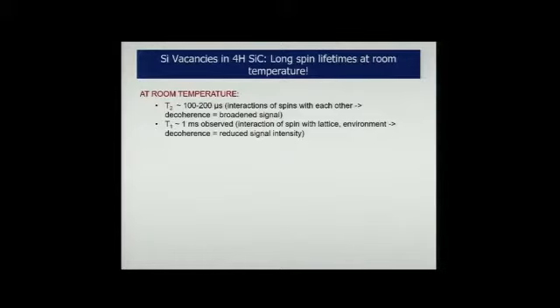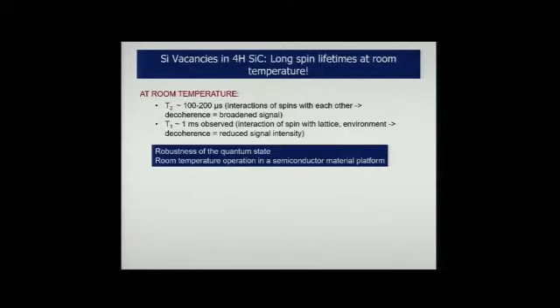And so decoherence has the net effect of reducing the signal intensity. These T2 and T1 times are on the order of hundreds of microseconds to milliseconds or greater. That is a long enough time, and there are ways of actually revitalizing the spin states. But those lifetimes at room temperature give us great hope for going further with these silicon vacancies as possible qubit candidates. So two other items on our wish list: the robustness of the quantum state, as indicated by the spin coherence lifetimes, and room temperature operation in a semiconductor material platform.